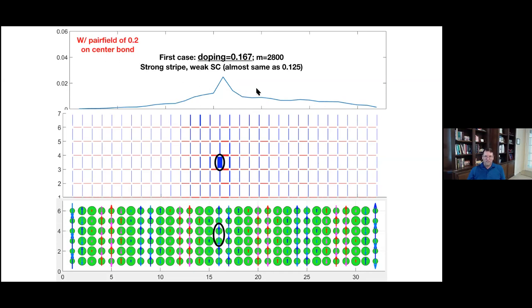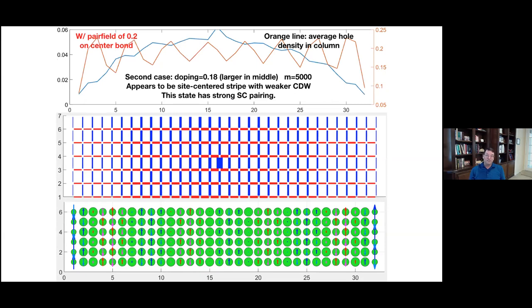But here's another calculation with a slightly different initial state. Here we see much more clearly a different state. The doping comes out a little bit higher, but we see a much stronger response to the pairing that persists all across the system. The pairing response is this blue line with a magnitude of 0.04, which is quite significant. It's got stripes. The orange curve is showing the density, so that's showing a stripe pattern. And you can see the stripes here.